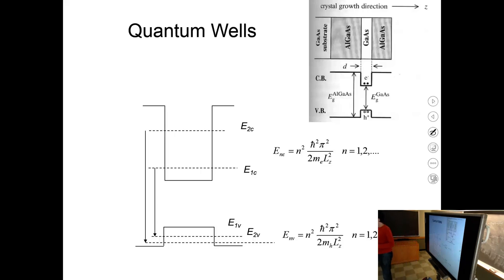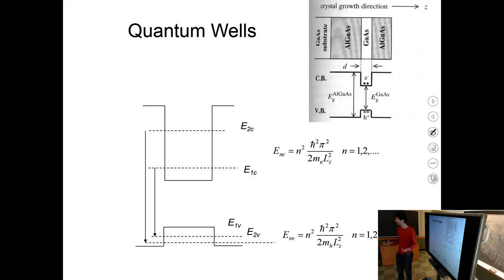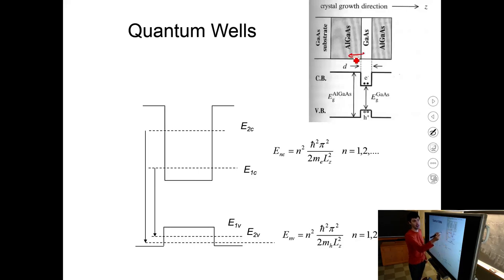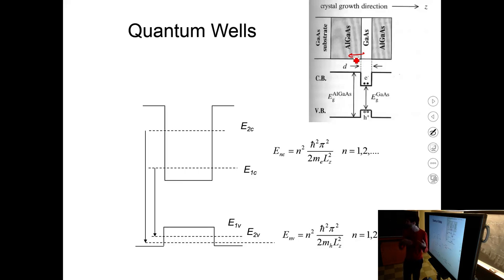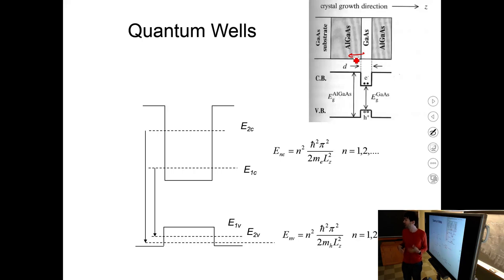MBE can produce all kinds of structures. One of the most common is called a quantum well — a potential well for electrons or holes in a semiconductor. This realization involves two heterojunctions: aluminum gallium arsenide / gallium arsenide / aluminum gallium arsenide. You can grow this in an MBE machine by switching between aluminum and gallium atoms. It is all perfectly lattice-matched, so as you go along one row of atoms you see aluminums, then just galliums, then aluminums again — but it's otherwise a perfect crystal.